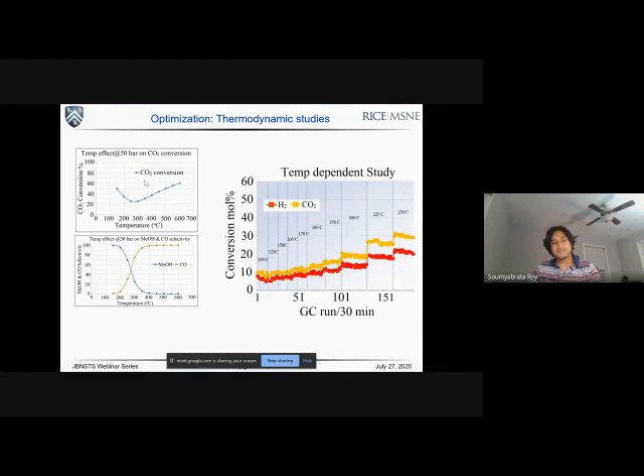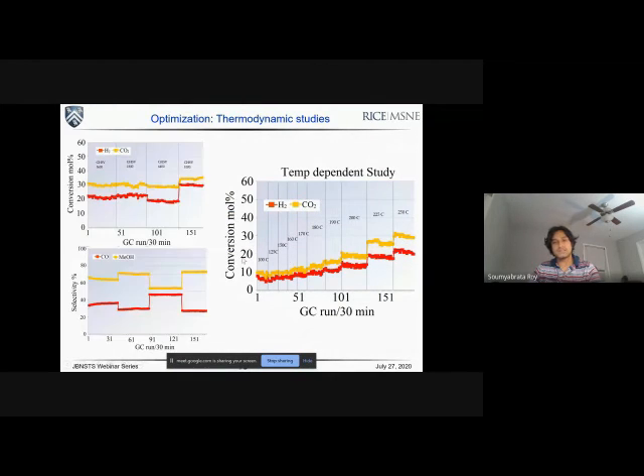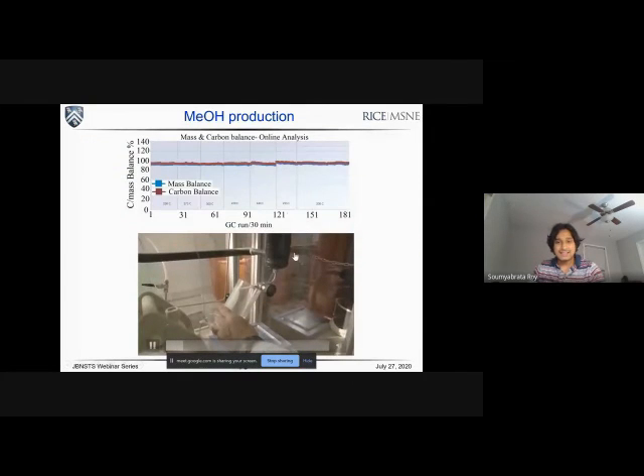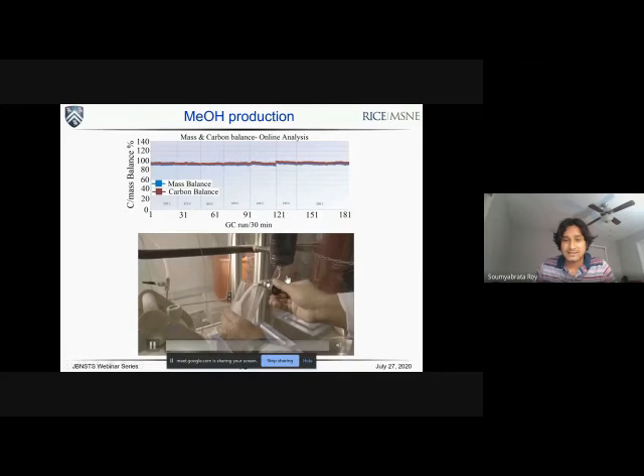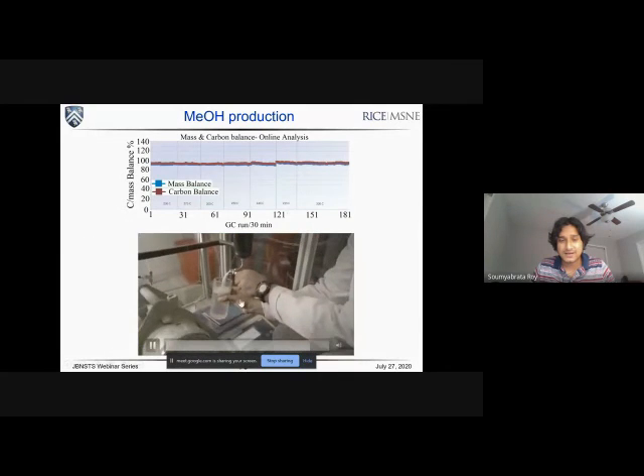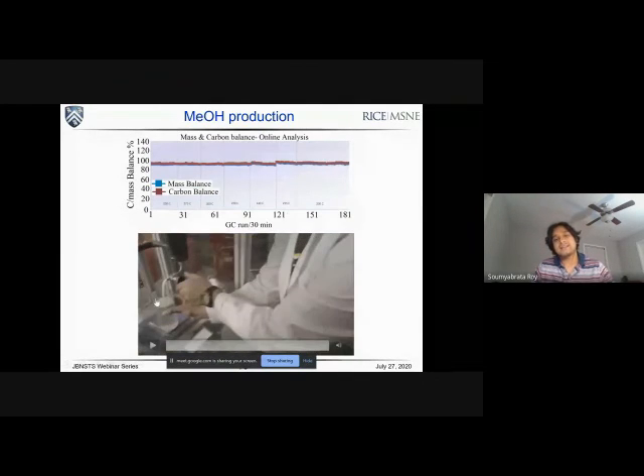You can see that with increasing temperature from 100 to 250 degrees Celsius, we could almost reach a CO2 conversion efficiency of about 30%, and the flow rates also have a strong effect on the conversion and selectivity. And here is a video showing methanol coming out of the reactor after 4 hours of reaction, and we could produce this liquid product. We also achieved a very high mass balance, which means there were no mass losses in our process, a very important criterion for industrial success.